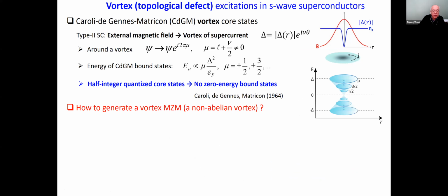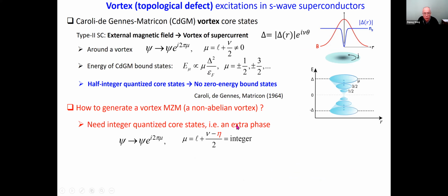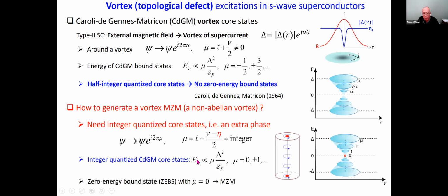So how do we generate a vortex Majorana zero mode? And that is how to generate a non-abelian vortex. If you look at the quantization condition here, you have to turn this quantization condition from half integer to integer. And in order to do that, you need an extra phase that I call eta here. Imagine I can do that. Then the core energy would be quantized by an integer. So it would start with 0, plus minus 1 and all that. And therefore, the one that sits at 0 with the quantum number mu equal to 0 is the Majorana zero mode, which is a pair of degenerate states that appears at the ends of the vortex line.